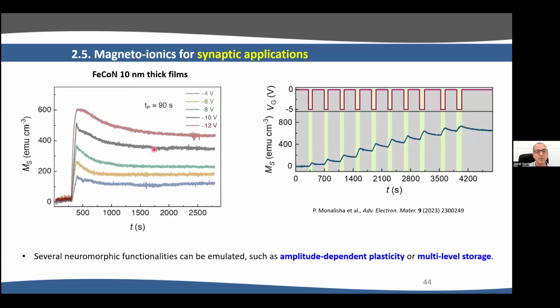So if you apply -4 volt, you can see you induce a bit of change in the magnetization and then it relaxes. But if you apply higher voltage, you have a larger change in the magnetization. It also relaxes, but will retain better. So this is a property of biological synapses, which is called amplitude-dependent plasticity. Depending on the voltage that you apply, the synaptic weight can increase, as you can see here.